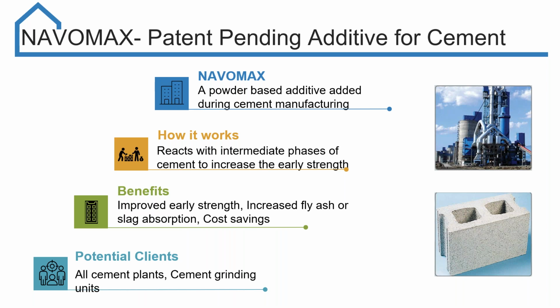Further, when we compare to the conventionally available additives for concrete and cement, even though we say it's a blend of micro minerals, we use only to an extent of 20% of micro minerals. If you look at the blends, they are pretty much in the same range of cement, and still able to provide the properties that are given by micro minerals.